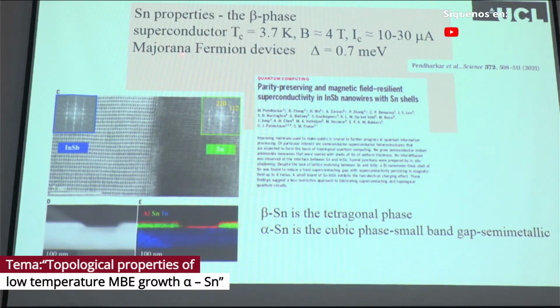But as I said, it's quite useful as a superconducting junction between tin and a semiconductor, where you might be able to stabilize a Majorana fermion in the gap, in the superconducting gap. That superconducting gap, energy gap, is about 0.7 meV. So we need to be really at quite low temperatures for these measurements. So most of these measurements are done in a fridge.